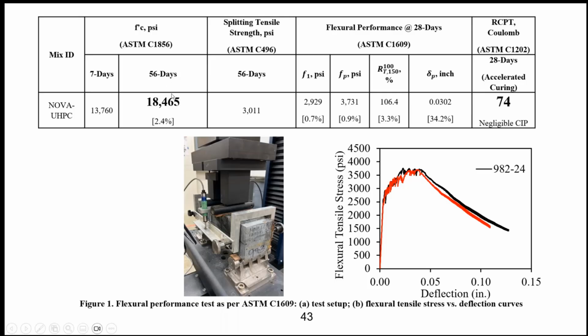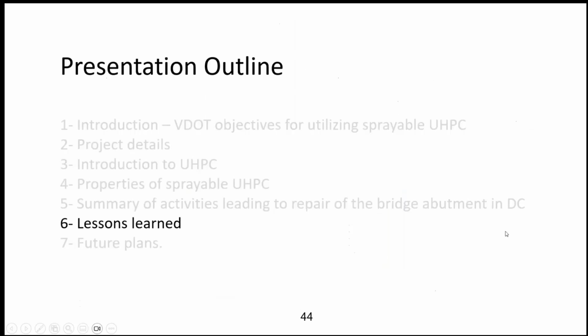Now these are the numbers for the UHPC that we used for the spray. This is not taken from the core sample. This is the UHPC that was used to spray. This data was provided to us by the Virginia DOT, by Sam Flaha Group. F'c was 18,000. The RCP was 74, basically. And this is a tension test that they did for us at the Virginia DOT.